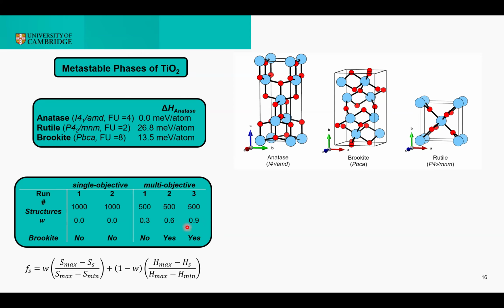In this case, the reference that I used was the experimental data collected at room temperature that I could find from the CCDC database. So the choice of the weight here that you see, this coefficient that tells how much importance we want to give to either the similarity index or the energy, seems to be quite important. Because if this weight is too low, meaning that we are giving more importance to the energy,